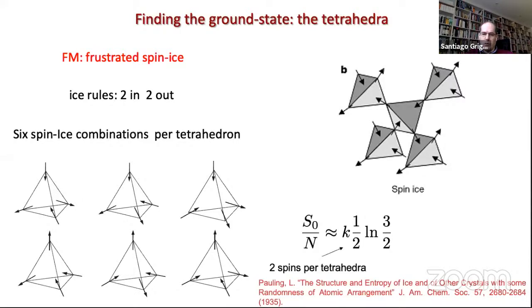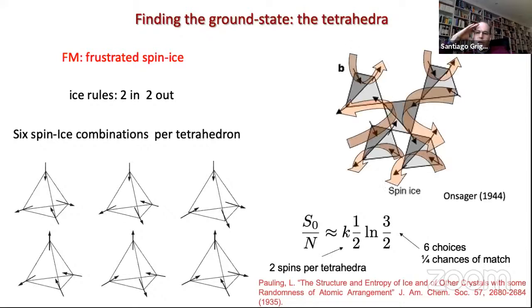So the way in which you can do this calculation is very easy. You have for each tetrahedron, because they are sharing, you have only 2 spins. So I have a factor of 1/2 here, and then of the 6 choices I had for one tetrahedron, there's a 1/4 chance of matching the spins with the neighboring tetrahedron, right? So that gives me the 6/4 becomes the 3/2, and this is the same number that you get for water ice, and that's why people call these materials spin ice.